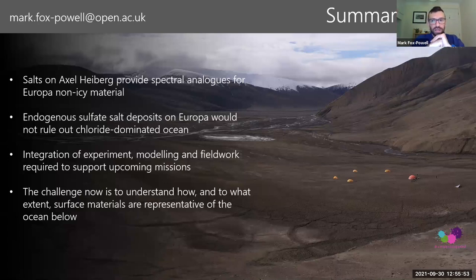But also, there's a couple of papers that identify colloidal silica associated with the plumes. This is why I mentioned colloidal silica in my slides. It's actually thought to exist in the ocean. It forms as a result of hydrothermal activity. But if there was a long residence time of this silica in the ocean, if it was kind of hanging around for a long time, it would nucleate and form much larger particles. So the size of these particles that Cassini encountered suggests a rapid transit time between the seafloor and space, effectively.